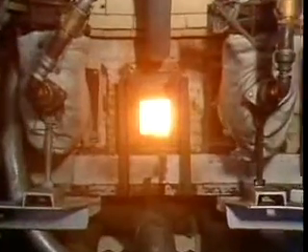In the furnace, the dry ingredients are heated to approximately 2,500 degrees Fahrenheit and gradually added to the contents of the furnace, 400,000 pounds of red, glowing, molten glass. Now watch as CertainTeed's advanced fiberglass technology transforms molten glass into fiberglass insulation. Below the furnace, liquid glass flows into a series of fiberizing machines,